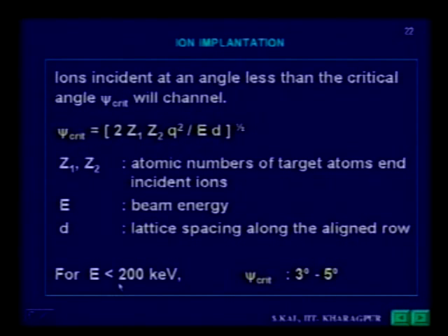It has been seen that if the energy of implantation is less than 200 keV, in that case, the psi critical, which is the critical angle, is in the range of 3 degrees to 5 degrees. That is the psi critical. Now,